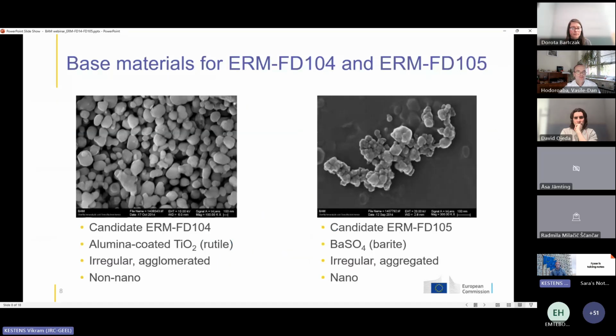And here on this slide, you see two representative electron microscope micrographs. On the one hand, FD104, which is an alumina-coated titanium dioxide. You can see it has an irregular, agglomerated shape, and the material is highly agglomerated. And according to the definition, this material is not nano, but it has a very small fraction of particles in the nanoscale. On the other hand, you have the FD105 material. It's not titanium dioxide, but it's a barium sulfate material. And you can see that it is much more aggregated. So it also has irregular particle shapes. And this material is a nanomaterial, so most of the particles have a size below 100 nanometers. And these were the two materials that we have developed.